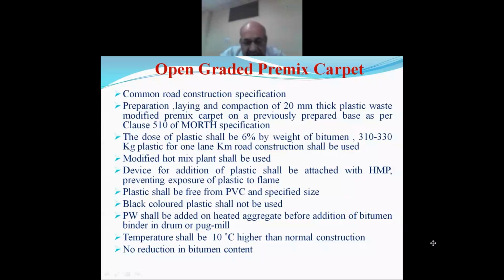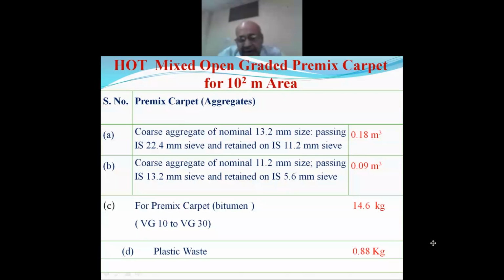Now I will take up the individual specifications like open graded premix carpet, which is a common road construction specification, particularly for low traffic roads. So, preparation, laying, and compaction of 20 mm thick plastic waste modified premix carpet on a previously prepared base shall be done as per clause number 510 of MoRTH specification. I again request you to keep the dose of plastic 6% by weight of bitumen, and in construction of open graded premix carpet 310-330 kg plastic shall be used for one lane kilometer road construction. So it is a ready reckoner for you.